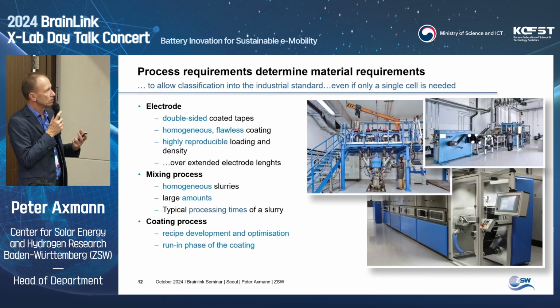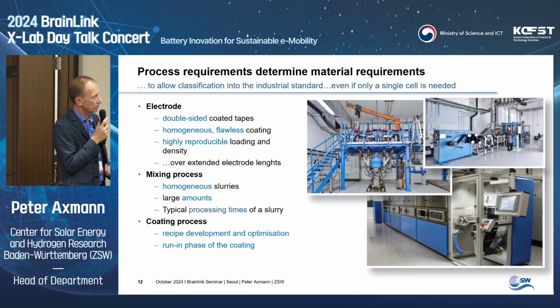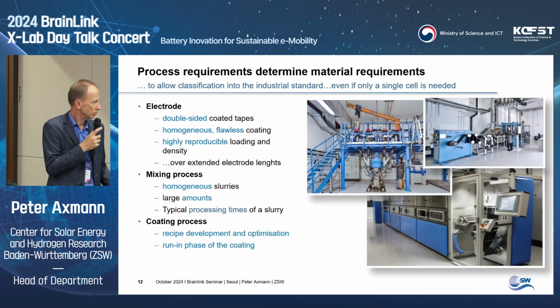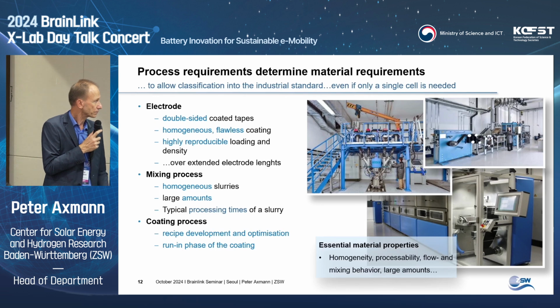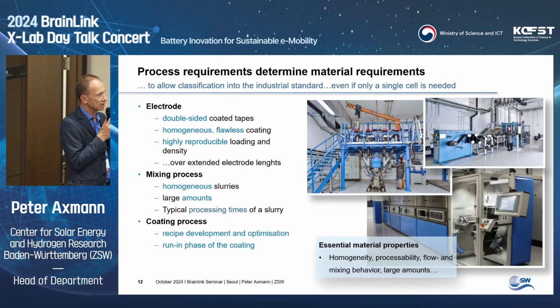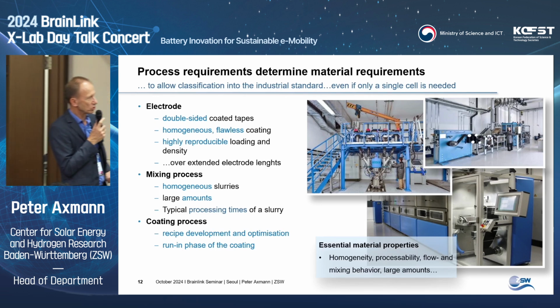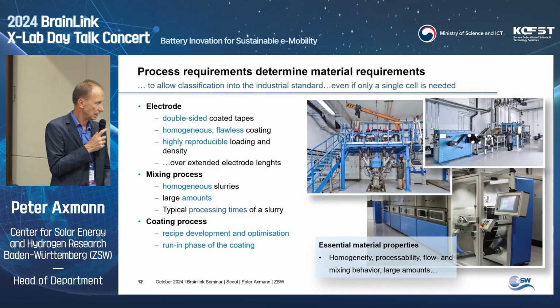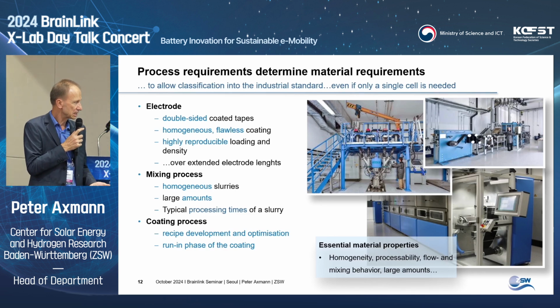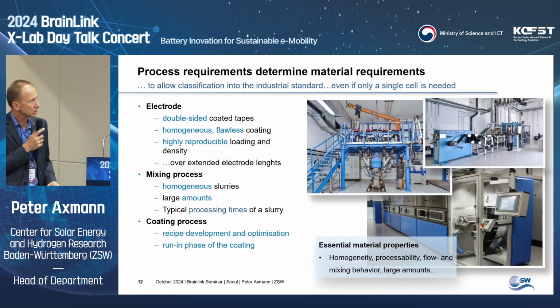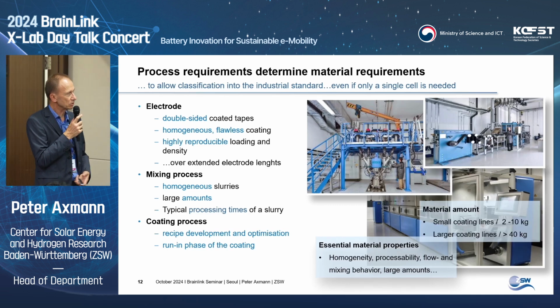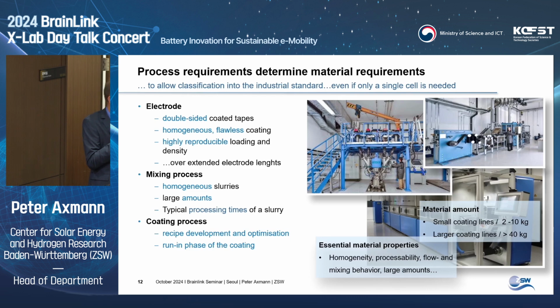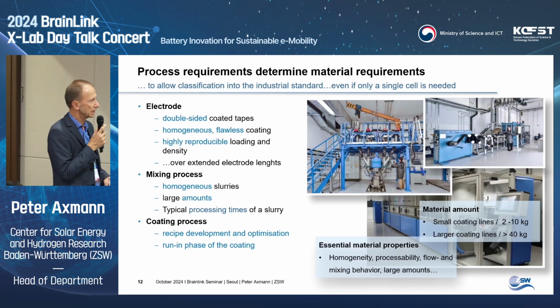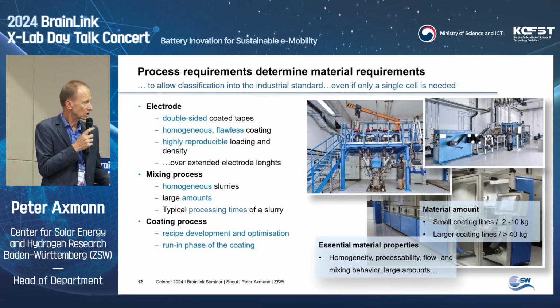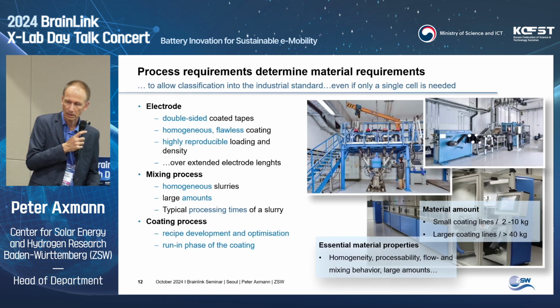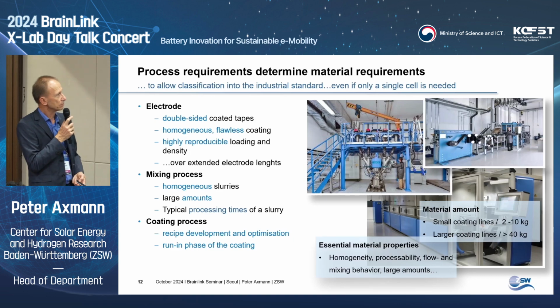In addition, to get this high homogeneity of the electrodes, you need homogeneous slurries. You need large amounts of that. And this has requirements for the material itself. So the material itself needs to be homogeneous. It needs to be processable. It needs to have a certain flow and mixing behavior, and you need to have it in large amounts to go to these machines. Yeah, and large amounts mean our small coating lines at ZSW need about 2 to 10 kilograms in one batch.